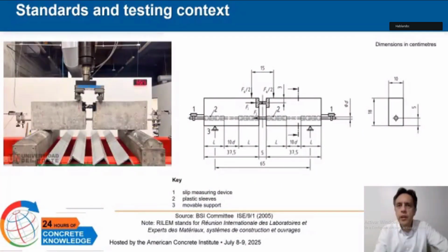This diagram illustrates the configuration of the RILEM RC5 hinged beam test, which was adopted for our study to evaluate the bond behavior between GFRP bars and concrete. The specimen is a 65-centimeter-long prismatic beam supported at both ends by movable supports that allow rotation and simulate flexural action. The GFRP bar is embedded along the beam's axis. However, the central region, spanning over 10 times the bar's diameter on each side, is intentionally debonded using plastic sleeves. This localizes bond activation in the central bonded zone.